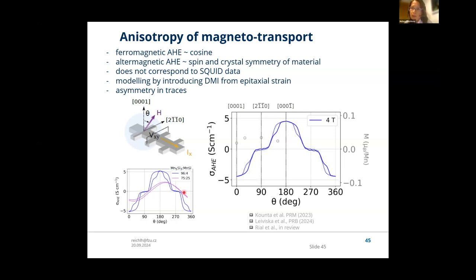Exactly. And in Mn5Si3, we are in a relatively lucky scenario that we can even manipulate the spins with the external magnetic field. This is a magnetic field of 4 Tesla, so it's not a small field. If we put iron or anything, the magnetization of iron would be fully following the magnetic field, and then indeed you would think about it like magnetic field cross product with the current. But here it's not so simple. Still, we have shown in the sweeps that we can control the magnetization, or altermagnetization, or however we want to call it, by the external magnetic field, that we can control the spins by the external magnetic field. Okay.